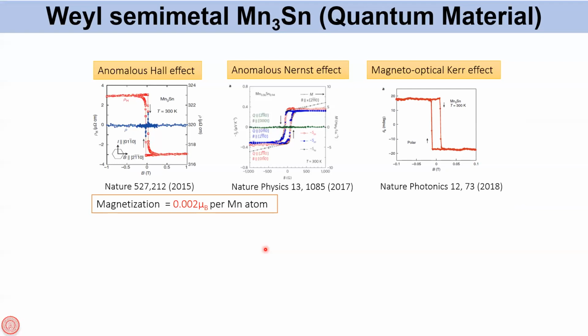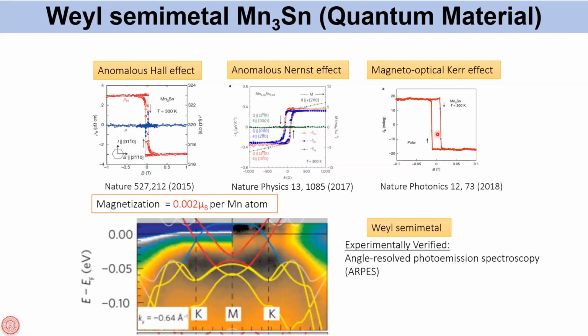Now I will change the material and go to another non-collinear antiferromagnet, which is known as Mn3Sn, and this also happens to be a Weyl semimetal, a quantum material. Although it is an antiferromagnet, it exhibits the anomalous Hall effect, anomalous Nernst effect, and magneto-optic Kerr effect, which are effects normally observed in ferromagnets. This is related to the fact that it is a special metal which exhibits so-called Weyl points near the Fermi energy, as has been observed in experiment. And this Weyl point leads to a large Berry phase curvature, leading to these anomalous transport properties in this material.